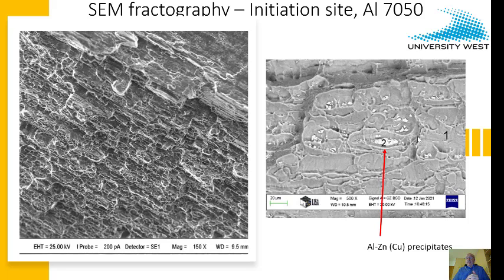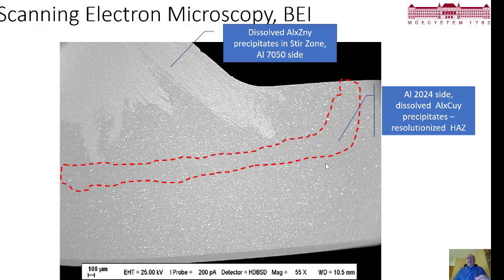There are some precipitates there coalesced in the middle of the grains, but most of them actually are precipitate free because we believe they all dissolved. We are in the process of doing some TEM work, but most of them dissolved. And based on this, we wanted to re-precipitate them by using an artificial aging process. But bottom line is that this is a ductile brittle combination mixed mode failure initiated at the coarse grain heat affected zone. So the large grains are the problem, obviously.